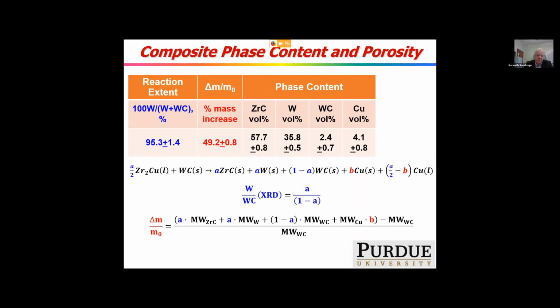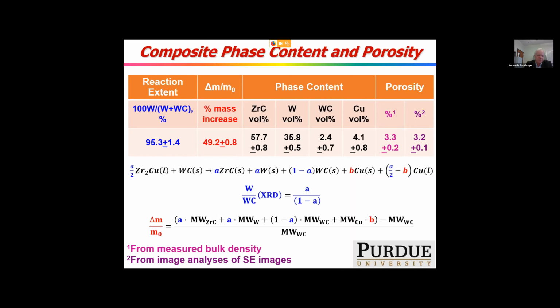Since we have the phase content, we can determine the theoretical density from real mixtures and then compare that to the bulk density. We typically get about 2 or 3% porosity, or 97% dense. That also compares similarly to the porosity we see from image analyses, which gives us pretty good confidence that we have the right porosity value. And so we know that these materials are quite dense, and we know their phase content using these techniques.